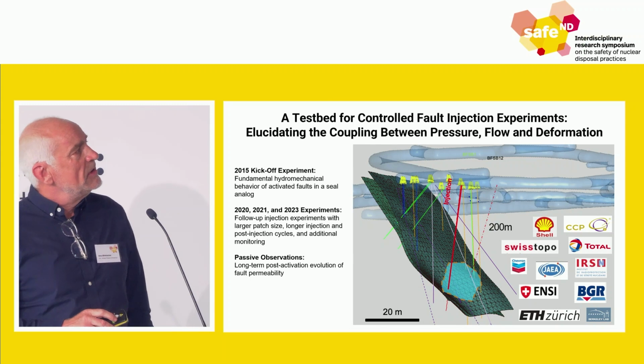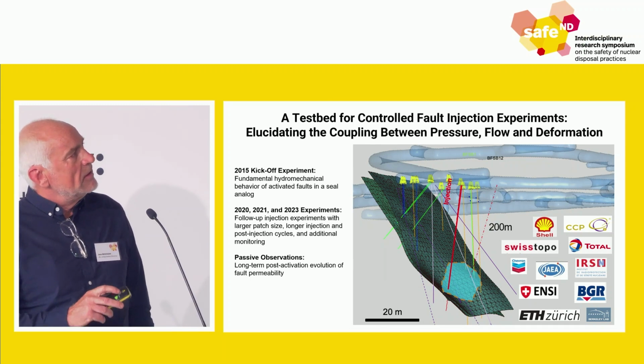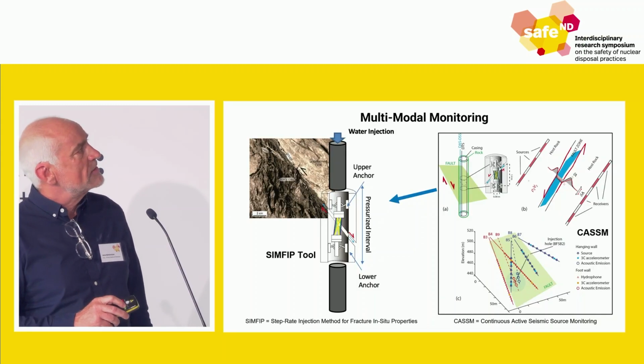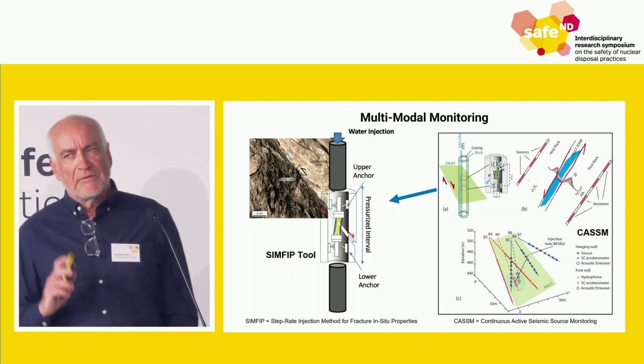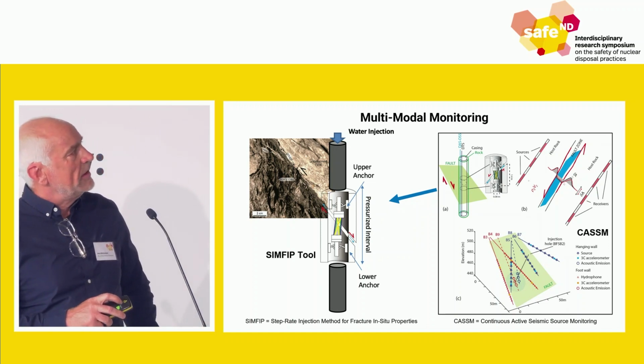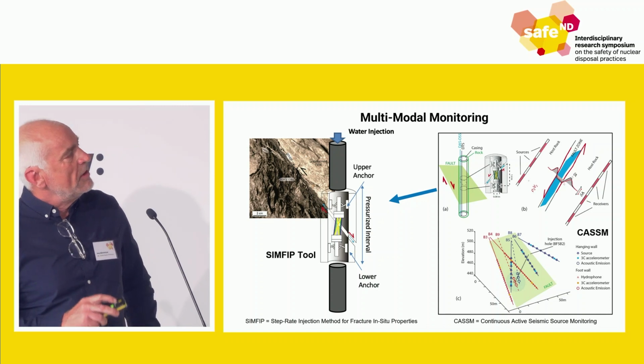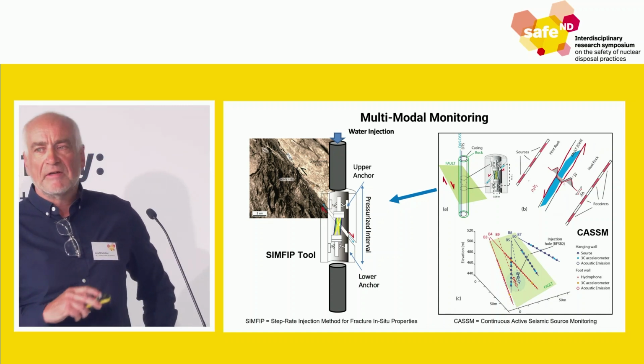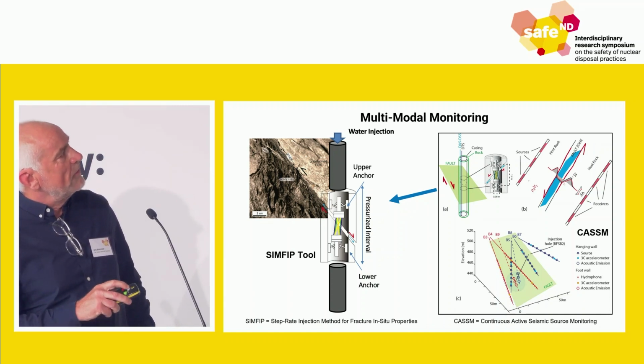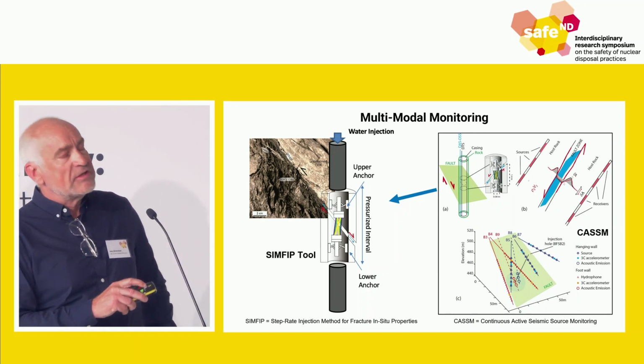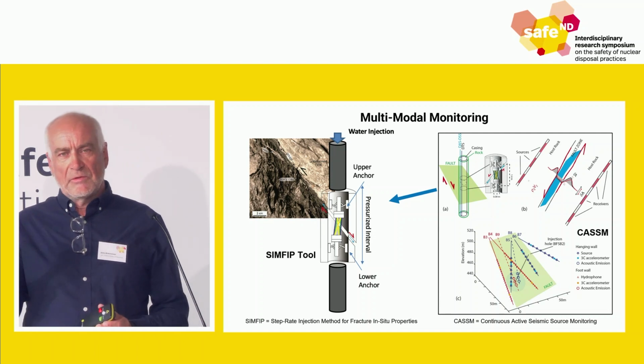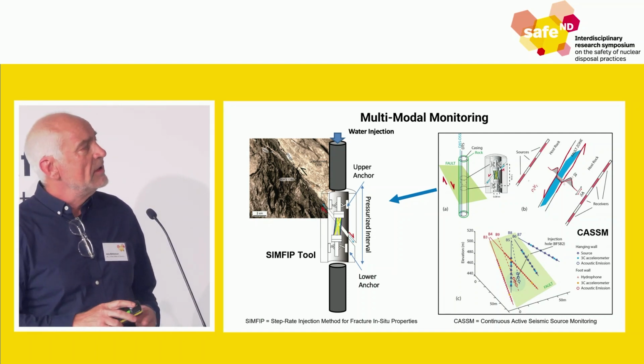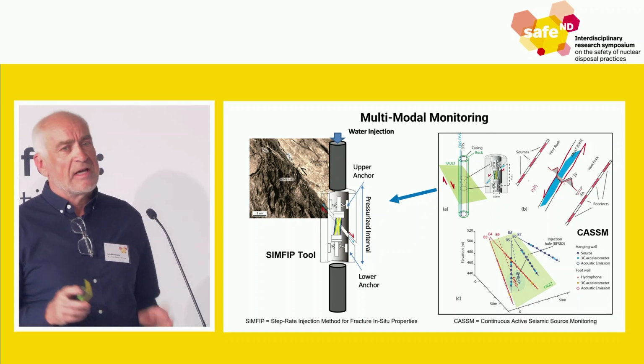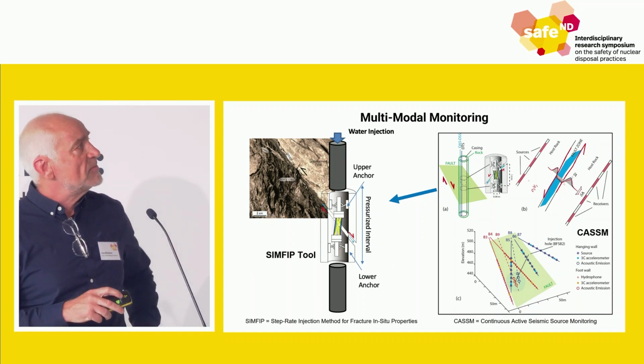So this is the setup. As I mentioned, we drilled into those faults, and one of the tools that my colleague Yves Guglielmi developed is shown here, which is essentially a packed-off system. You drill through the fault, clamp it at the bottom and top, and you have a deformation cage which gives you the three-dimensional displacements, gives you rotation as a function of time, at very high resolution in both time and space.